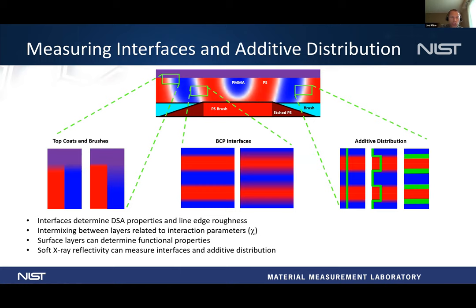And so for the next part, looking a little bit closer, there's a lot of interest in these interfaces because you want to make very smooth lines. In looking at different materials, sometimes you have to do tricks to get them to stand up, where you put a top coat on there. We can do very similar measurements to what I showed before with the soft X-rays, but use reflectivity instead, look at vertically oriented films, and get a depth profile of the chemistry.